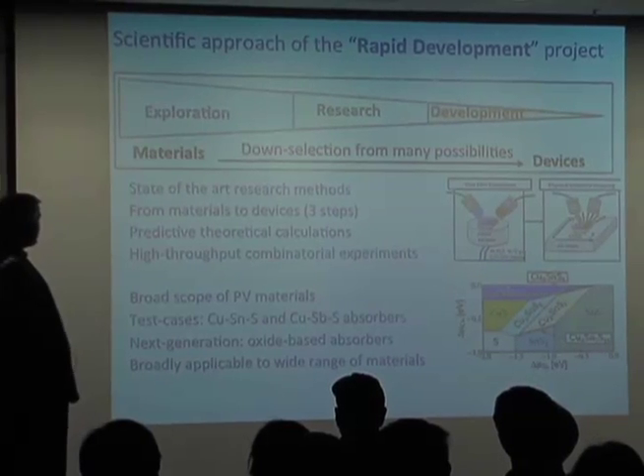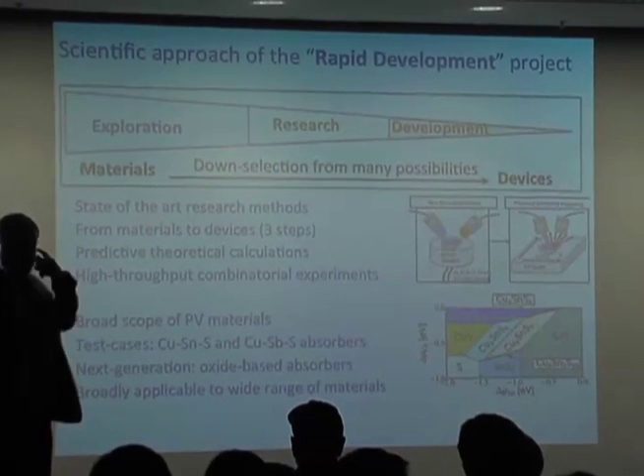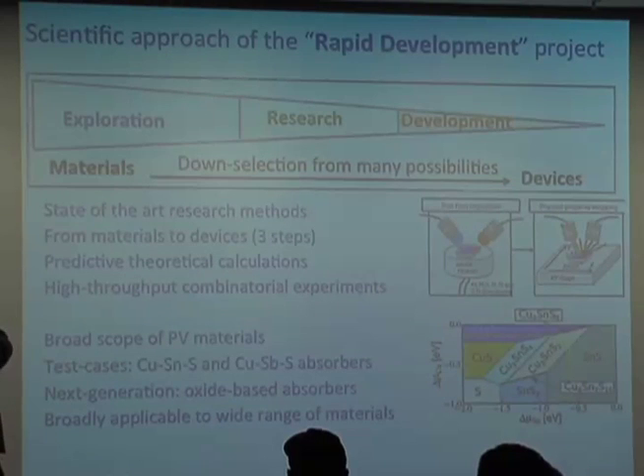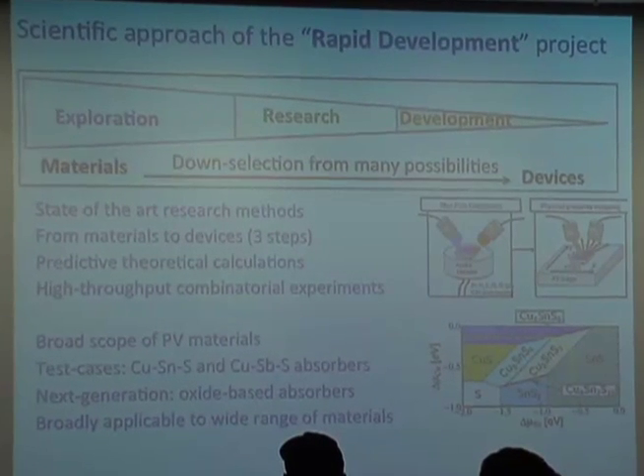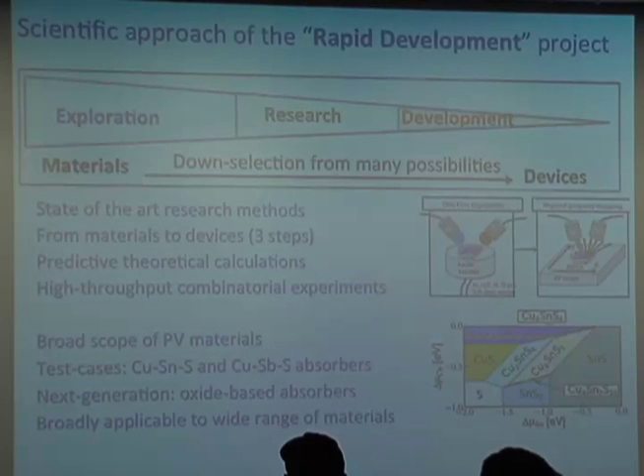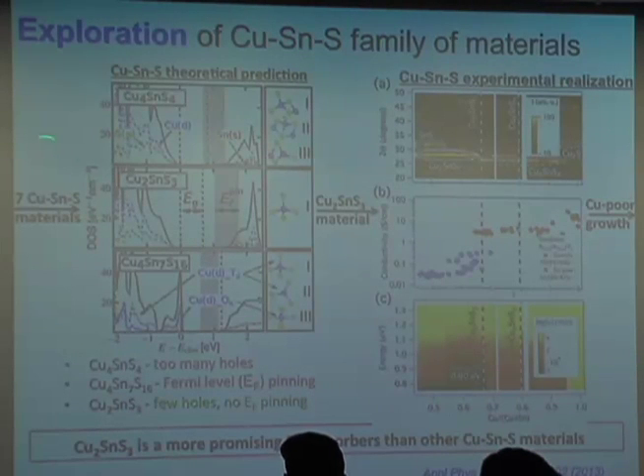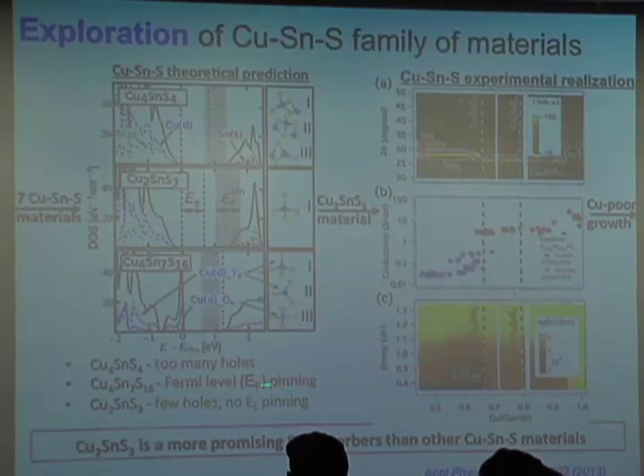And in fact, we're using this methodology now. I think one of our key successes has been taking this methodology and transferring it to our more applied programs. So in our applied programs at NREL, we've been very interested in understanding how we might rapidly develop some of these known absorbers, whether they're the copper antimony sulfide systems or the copper tin sulfide systems. And we've been able to do this very similar type of method where we've looked at 7 different copper tin sulfur systems and down selected by looking both at the absorptivity and the densities of states, some of the other issues with too many holes in some of these systems, Fermi level pinning in some of these other systems,